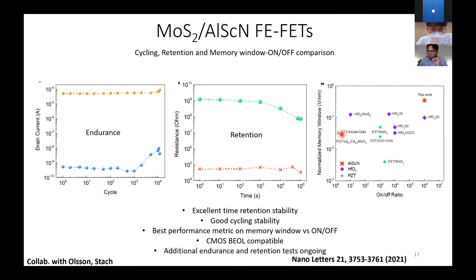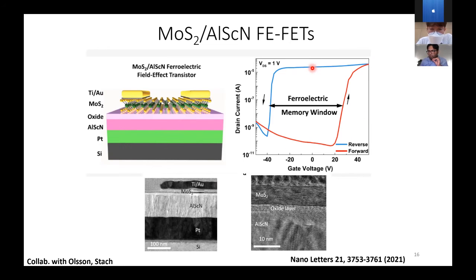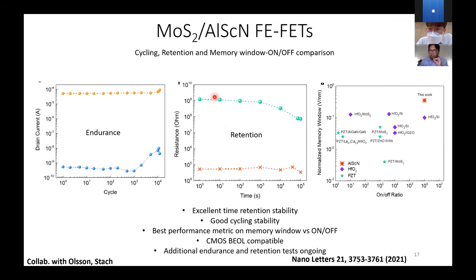But nobody believes you that you have made a memory device until you show endurance and retention. So we have done some endurance measurements, and the devices are stable up to at least 10,000 cycles, maybe even more as you cycle them. And then the charge state, which is the low resistance state and high resistance memory state, right? They can be stored for at least 10 to the power 5 seconds. So this is actually very, very advantageous.